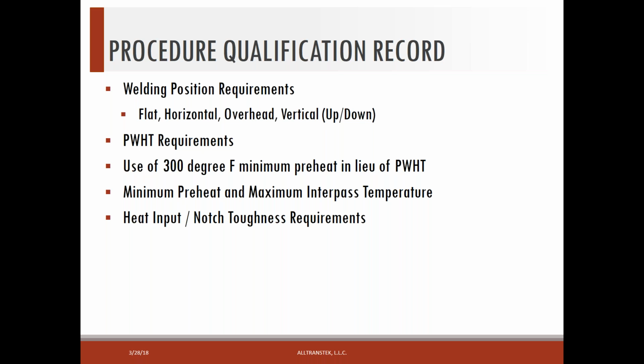However, if I'm going to weld a test coupon and I do have notch toughness properties specified, then typically most codes say that if I weld that coupon in the vertical up position, that's the most severe case for notch toughness. Why is that? Because that's the most heat input, the slowest travel speed, and the most severe condition that we would see in a production environment. So if I qualify in the 3G up position with notch toughness requirements, then I can weld in any position per the procedure, simply because heat input has an adverse effect generally on notch toughness properties.